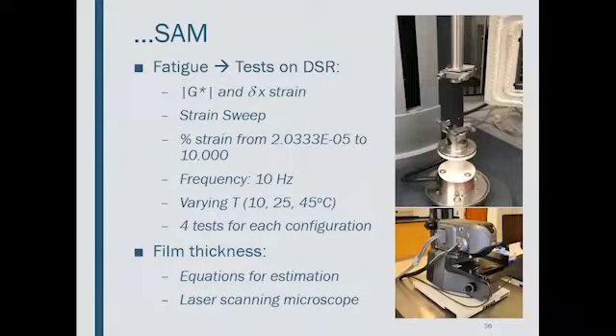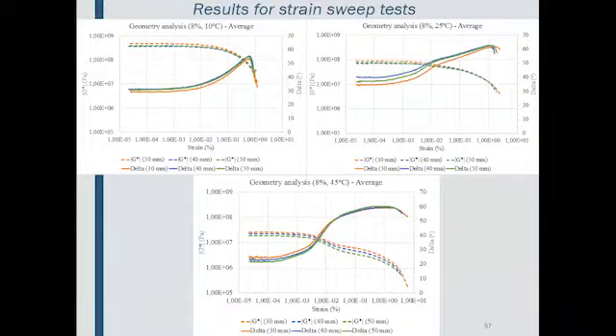We also tried to figure out the film thickness using 2 procedures: estimation by equations and images with the laser scanning microscope. This is an example of the results that you get. This is for 8% dosage at 3 temperatures and also in the 3 geometries. So you can see the relation between the parameters: complex modulus, phase angle, and strain. We can see the failure point in all tests. And you also can see the influence of the temperature, because depending on the temperature, we got different shapes for these curves. We just finished these tests, but now we will start to analyze the results.